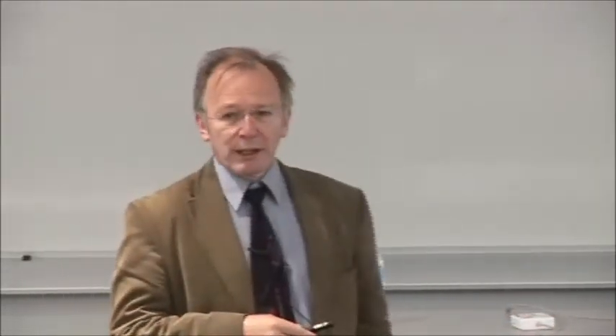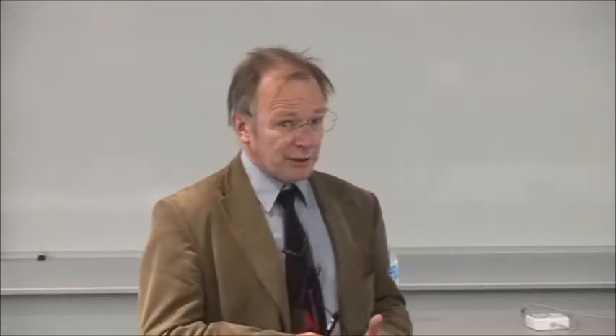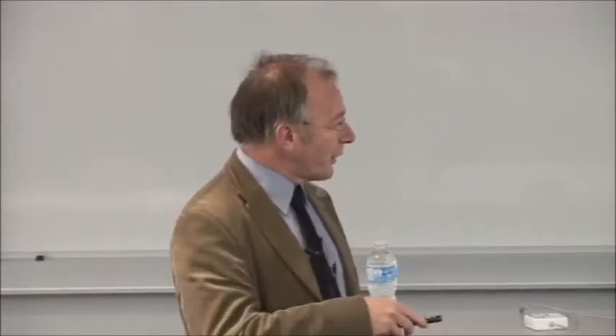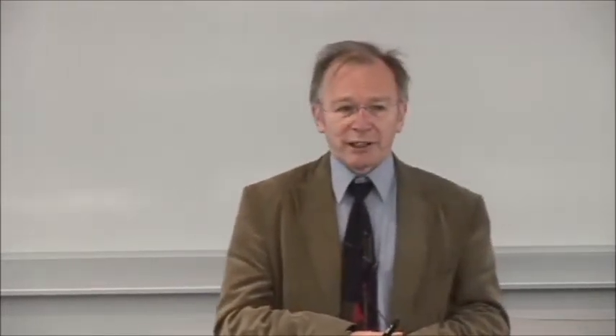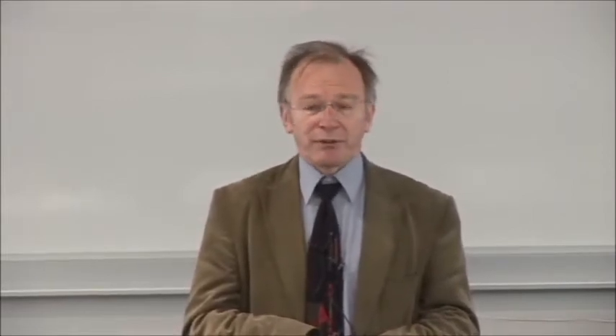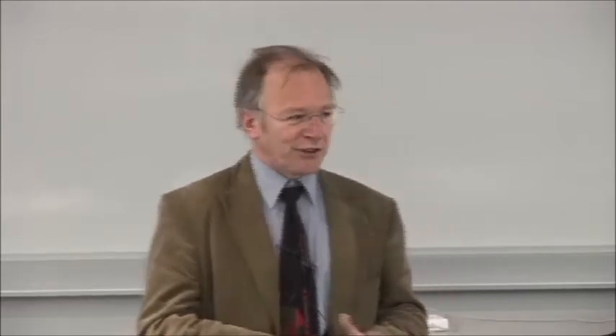Secondly, we don't really want to have a force that distorts the sample or biases a process. So we want to put as low a force as possible, and we've addressed that in 2 ways. So I'll mention that. And finally, something that we've almost forgotten, as SPMers, is that our samples are nearly always planar. In fact, we don't even think about not imaging a planar sample. That's a clear restriction, because life isn't planar, life isn't two-dimensional. So how do we look around a 3-dimensional object? That will come towards the end.